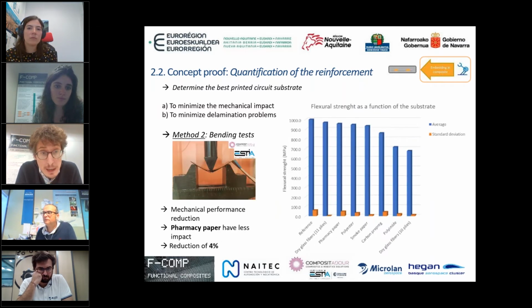Second test was checking these samples against bending. In here, we saw as well the same issue. In this case, we have the reference on the left. Sorry for these mirror images. And you can see as well, there is a decrease in the mechanical performance of the material. But again, pharmacy paper is the one that has less impact, only 4% reduction.